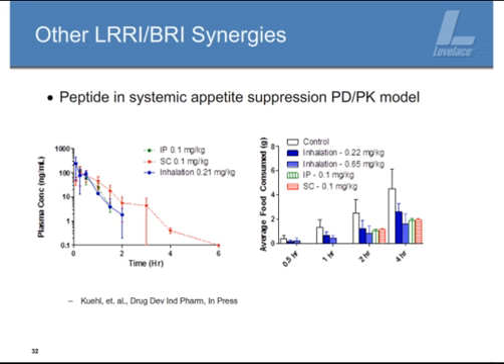So on the left, you can see that following a dose of 0.1 mg/kg by IP or sub-Q, we see similar systemic pharmacokinetics. Through the different doses and different modeling of the pharmacokinetics following inhalation, we determined that a dose of 0.2 mg/kg by inhalation resulted in similar systemic pharmacokinetics.